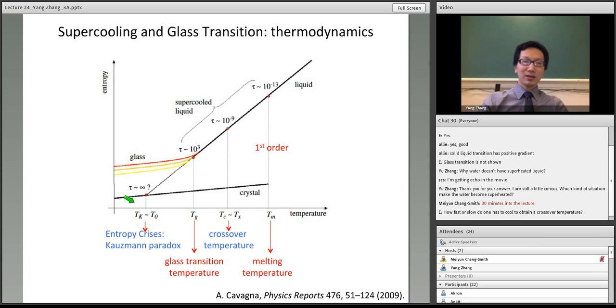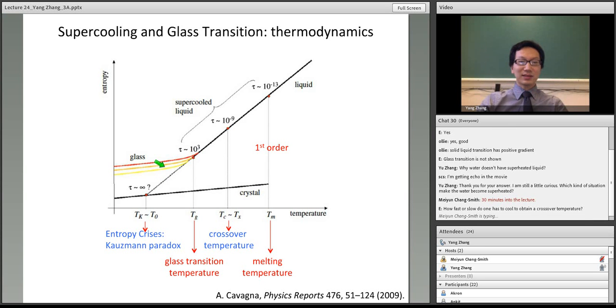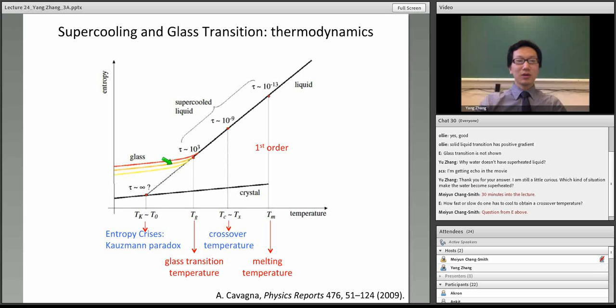But by extrapolating the entropy of the liquid, we can get the Kauzmann temperature. It's also called the entropy crisis, sometimes also called the Kauzmann paradox. It's basically the temperature at which the entropy of a supercooled liquid or glass becomes the same as that of a crystal. So when we go below that temperature, it's against our basic sense of thermodynamics. In order to explain this Kauzmann paradox, obviously, we can assume that above this temperature, an underlying thermodynamic phase transition has already happened. So there might be a unique state of glass, the so-called ideal glass state.